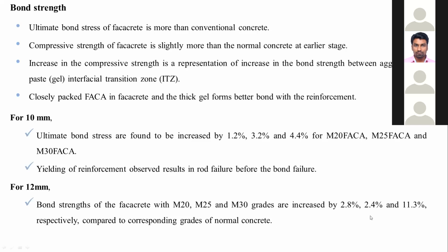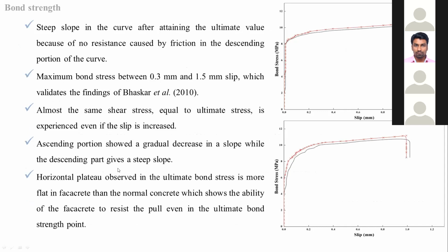For 10 mm reinforcement, as I explained before, yielding of the reinforcement was observed, resulting in rod failure before the bond failure. And for 12 mm reinforcement, we found a bond failure due to the shear force, shear failure. So in general, we can generalize our graph curve into three phases. There is one initial phase, which is a linear curve, and then a small gradual increase, then the failure curve.